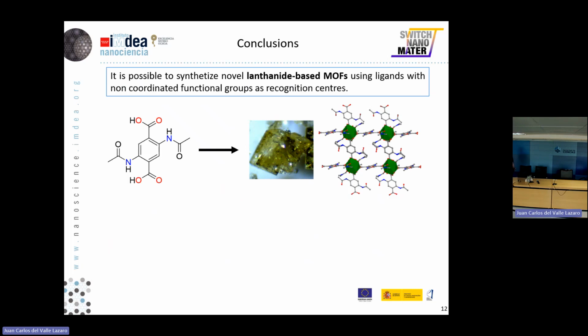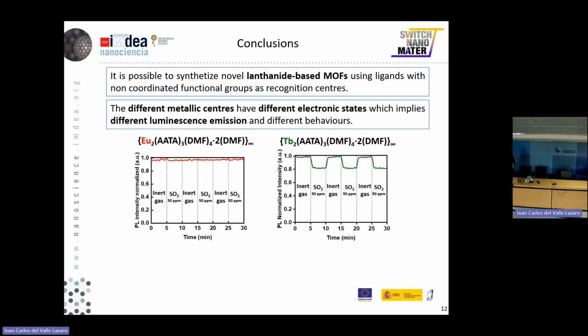Finally, we have demonstrated that it's possible to synthesize a novel lanthanide-based MOF using a ligand with no coordination functional group as a recognition center for different pollutant and atmospheric gases, with different metallic centers that present different coordination states, which implies different luminescence emission and different behaviors as the pollutant passes through the material.